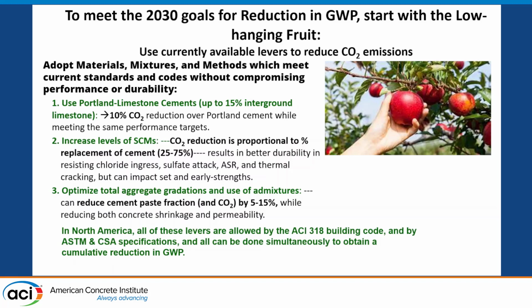concrete, you get better quality concrete, because permeability of concrete is related to the paste fraction. The more paste you have, the higher the permeability for a given mix, and you're going to have more shrinkage and volume change because that's related to the paste fraction. So it's a low-hanging fruit that could save another 15% of the CO2 just by changing the cheapest thing in your mix, often the aggregates. But it requires more bins at the ready-mix plants, and it requires a little more optimization work.